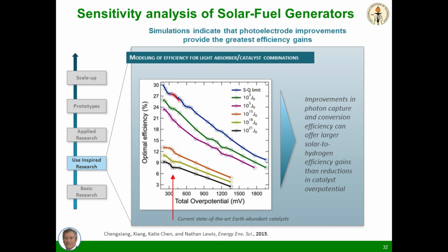And what we've shown is that no matter which curve you're on, increasing the catalytic activity by another 50 millivolts, going a little more to the left, will barely make a difference in efficiency. What makes the most difference is matching up these light absorbers. And so we set our efforts to try to match up the light absorbers to remediate that deficiency that we had with tungsten oxide being the only good material we had, but not good enough.